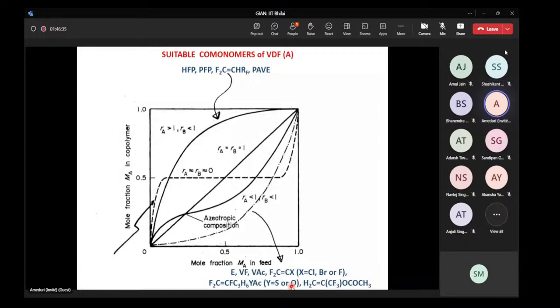And so you have to drive the good conditions. There are also this kind of monomers we also prepare in the lab, on which we study the reactivity ratio, in which on one side you have a better reactivity of this monomer, but on the other side, on the other concentration window, you have a higher reactivity of VDF, this being called the azeotropic composition. And then the last family of comonomers is when, whatever the feed concentration of both comonomers, you are on the way to be about 50-50.